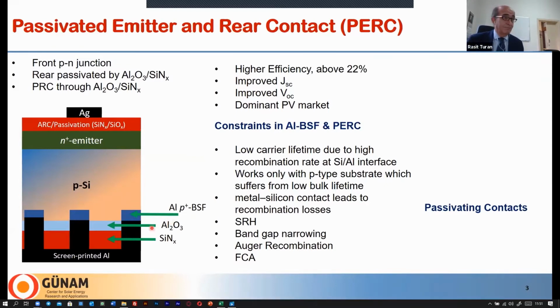The most common feature that limits the efficiency of aluminum back surface field and PERC is the direct application of metal with silicon. And this metal silicon contact leads to lots of recombination losses of electrons and holes, because there is a high density of active states at this interface. And these states usually lie within the band gap of silicon. Well, the use of aluminum back surface field or boron doping can reduce this effect.